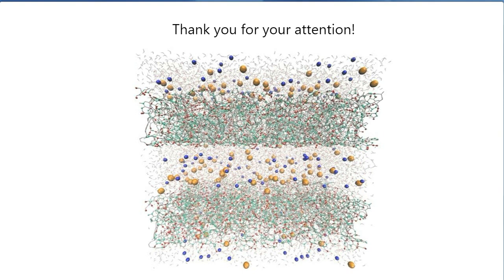More recently, Romain did some cesium calculations, and to our surprise — because we let the carbon atoms move in the simulation, inducing some breathing of the electrode — we were seeing cesium ions, which are pretty big atoms, getting into the pores. So at the end of the day, it will be very interesting and maybe crucial to allow the breathing of the electrode to well understand the docking of different ions in the pores. To answer your question, for now in a rigid situation, the optimal pore size in the five-to-seven angstrom range is really in favor of sodium ions more than chloride ions. But who knows once we allow the carbon atoms to move.